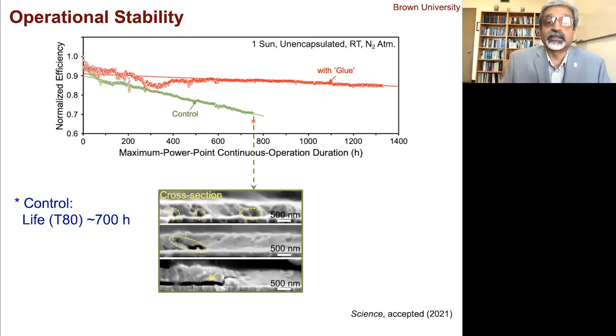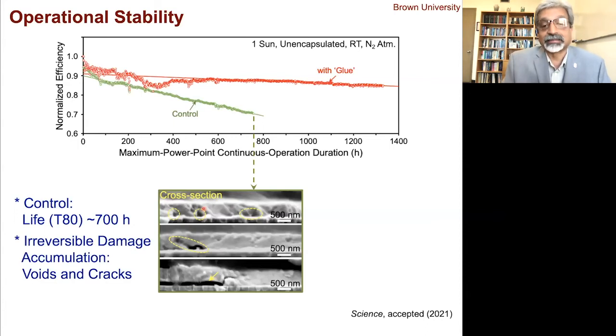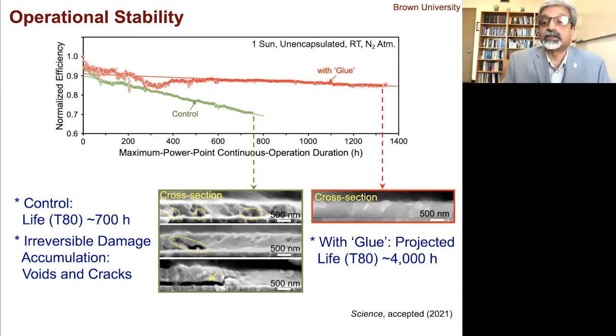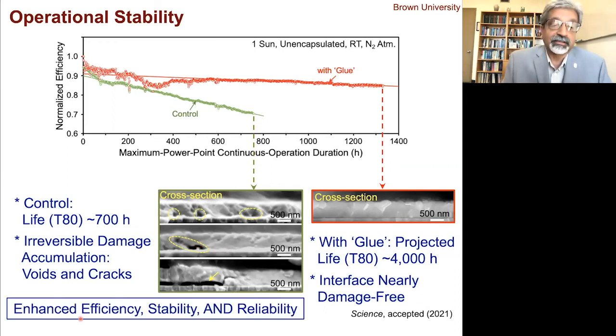And when we break open these solar cells after testing, what you find is there are voids and cracks at this interface. And that is because this interface is not very tough. But when you toughen the interface with this glue, the projected life here is actually about 4,000 hours. And when you break open the solar cell, you see that the interface is relatively pristine. It doesn't have these holes and cracks, right? So now we have enhanced efficiency, stability, and reliability using these interesting approaches.